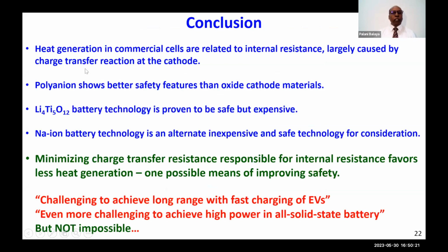So in my conclusion, heat generation in commercial type cells has been discussed. I related it with the internal resistance, largely caused by the charge transfer reaction at the positive electrode. Polyanion shows better safety features than the oxide chemistry. Lithium titanate is very good for fast charging, fast discharging, but it's pretty expensive. Sodium-ion battery technology can be an alternative, inexpensive, and safe technology. So minimizing the charge transfer resistance, as an example I showed, can help minimize the heat generation, one possible means of improving safety.